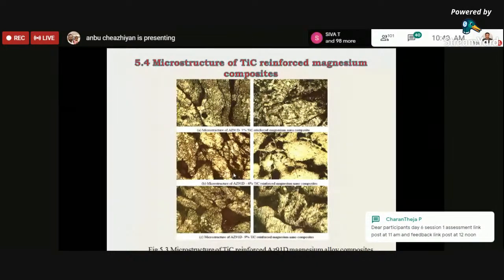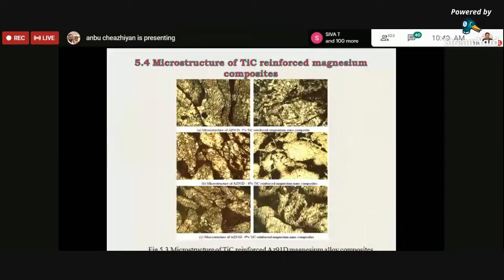From this microstructure, it has been observed that the magnesium powder has been sintered effectively with good fusion, along with the formation of secondary phases. Fusion of primary magnesium powder leads to better bonding of composites. The matrix has secondary phases precipitated at the grain boundaries, in addition to alloying elements also observed in the matrix alloys. The grains present in the magnesium matrix appear as a lamellar structure.